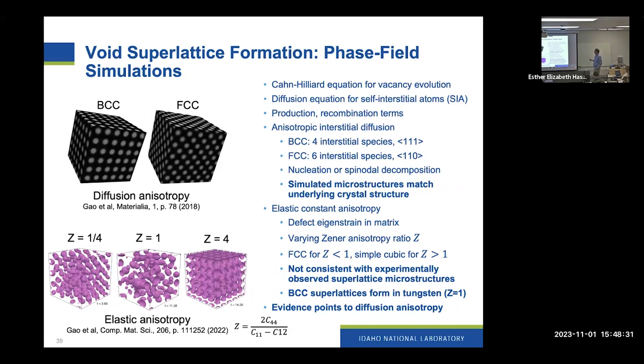To look at the effects of anisotropic diffusivity of these interstitials, we looked at BCC materials and FCC materials. With these individual crystal structures, we looked at how many different unique directions there are for diffusivity, and we introduced one species that has enhanced diffusivity in each direction. So 4 different types in BCC, 6 different types in FCC. Whether the superlattice is formed by spinodal decomposition or nucleation, we saw that the simulated microstructures always matched the underlying crystal structure. So that's good. That matches experiment in most cases.